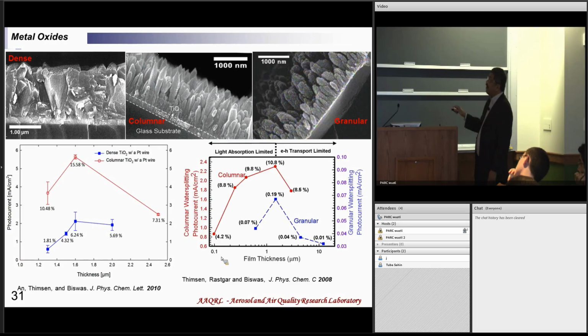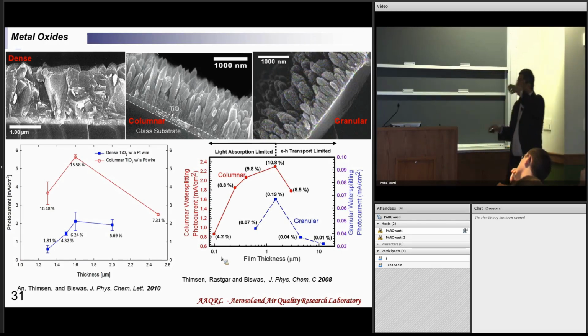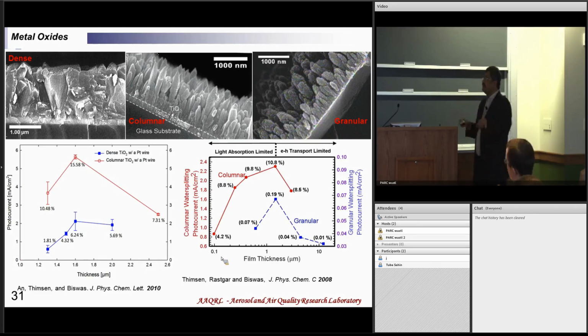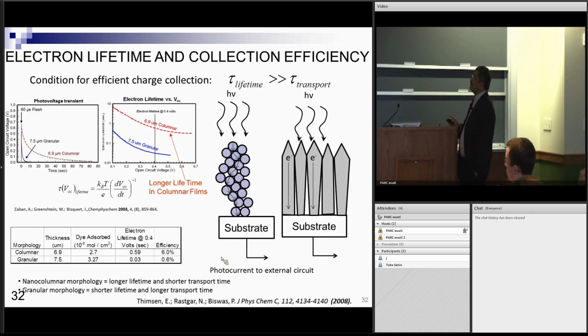And there is an optimal thickness, because once I go beyond a certain thickness, the electron has to traverse a greater length and could be lost. So as I grow these films to be thicker and thicker, they of course harvest more sunlight, but most of the electrons are lost. Okay, so we can do studies like that to find out the effectiveness.